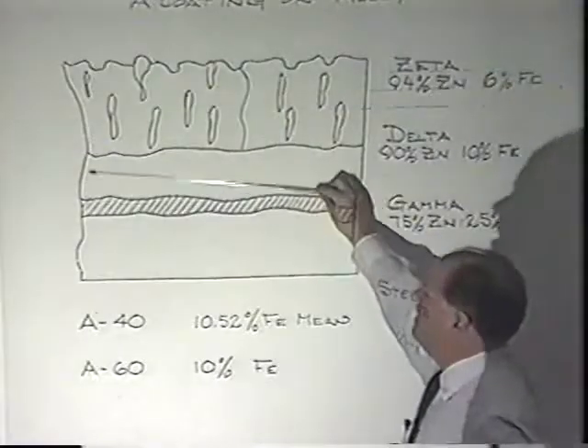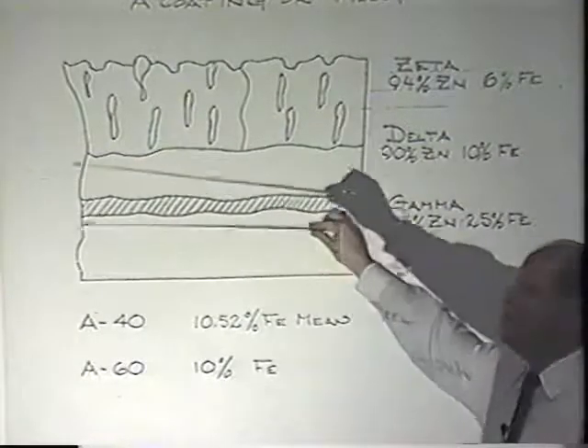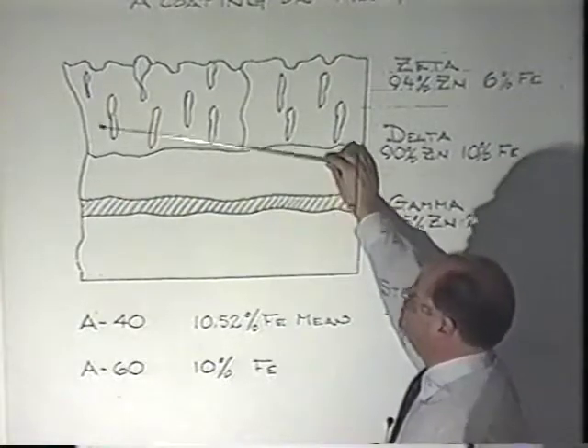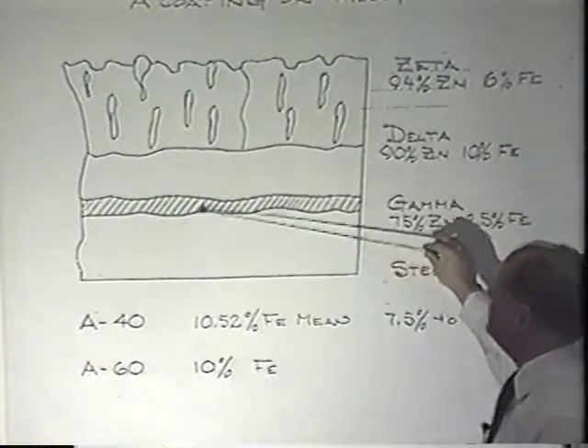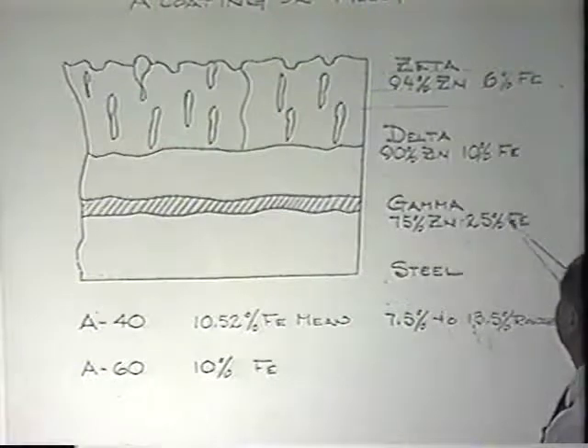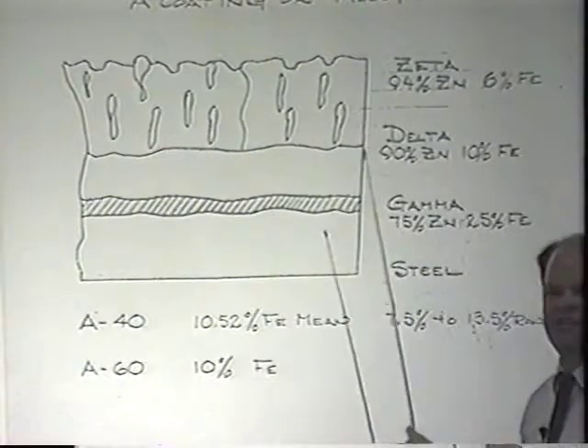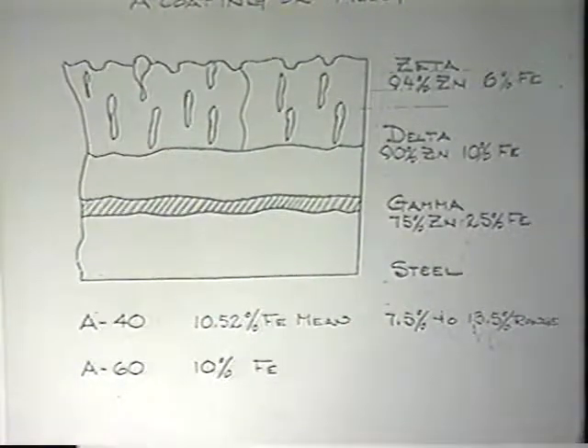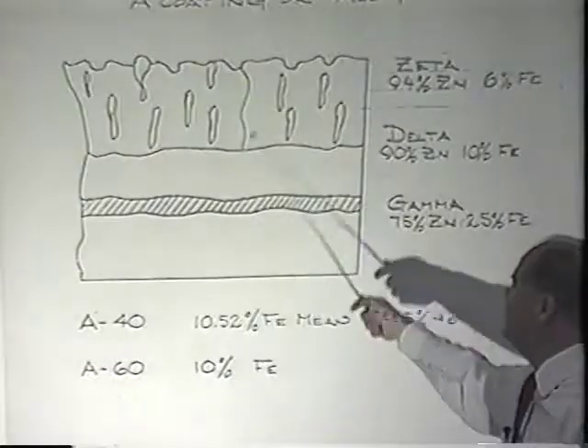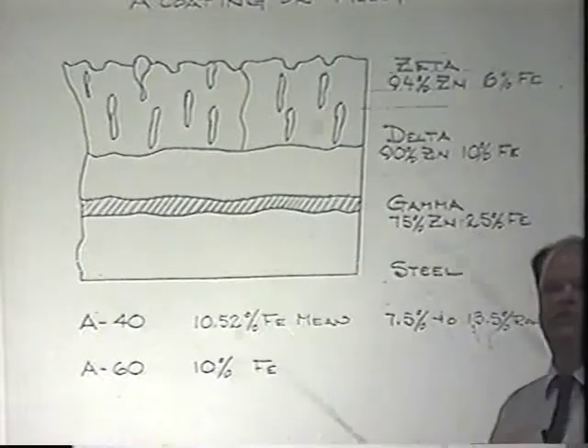Now on the galvanized, there was just a little bit of an alloy layer in here. On the galvanneal, since we allowed that to go all the way to the surface, close to the interface here, you have an alloy. It's a very high iron content. This is a very brittle alloy. It's not very strong. So when you bend this piece and form it, sometimes you can have some powdering where it'll start flaking off right here. And your coating will start flaking off.